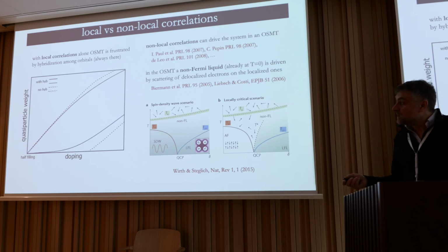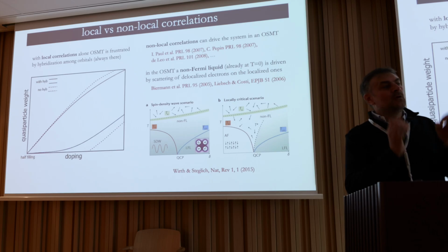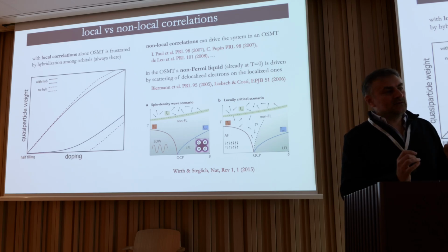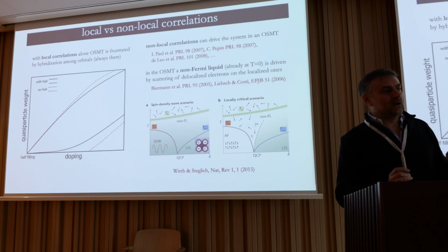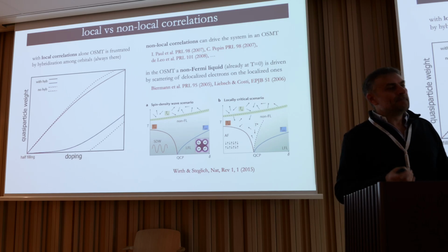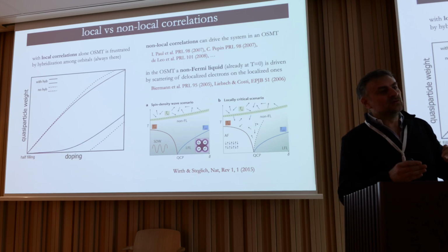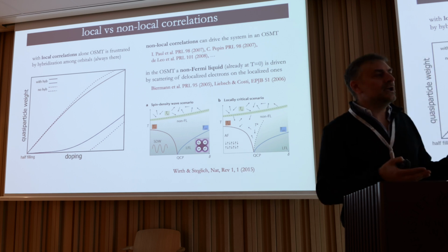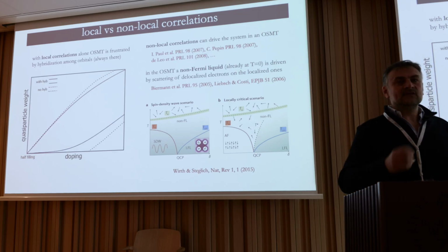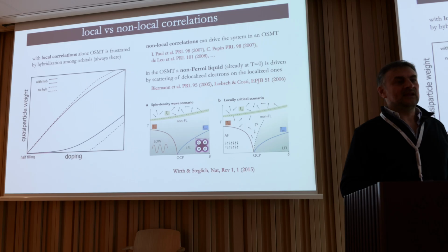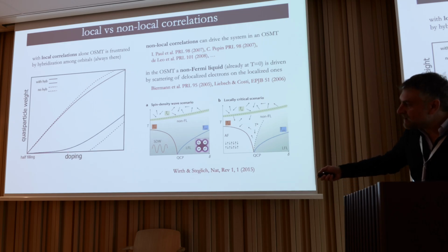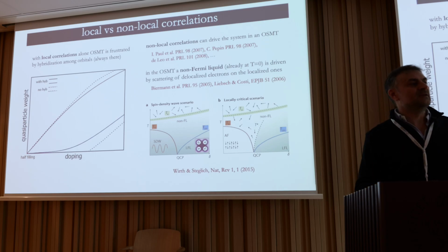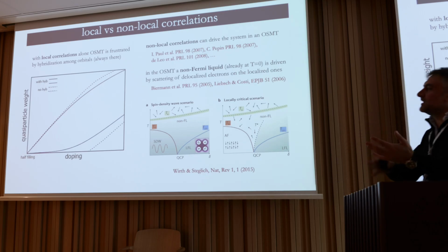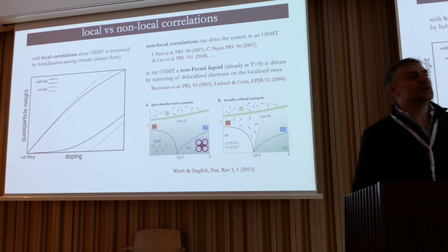And secondly, you can show mathematically, quite rigorously, that local correlations cannot induce an orbitally selective Mott insulator in these multi-orbital cases, because the energy to localize just one kind of electron would be too high. On the other hand, if you include non-local correlations, RKKY or these kind of things, then you can obtain an orbitally selective Mott insulator. So this behavior of extremely heavy electrons never wanting to localize can actually be cut here if non-local correlations prevail, which means you can find several kinds of Doniach phase diagrams, discussed traditionally in the f-electron case.